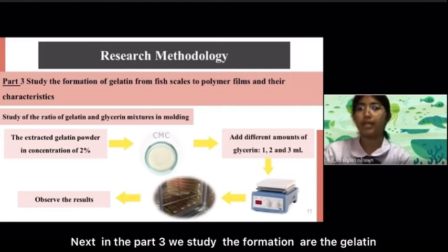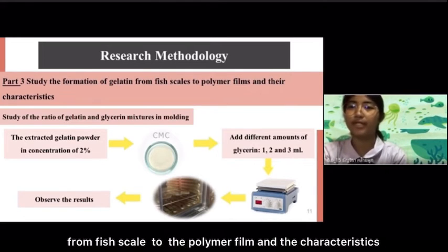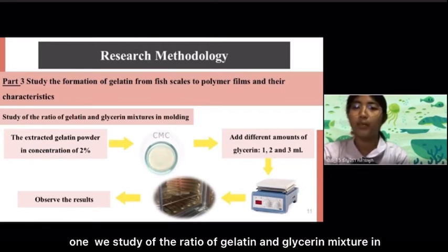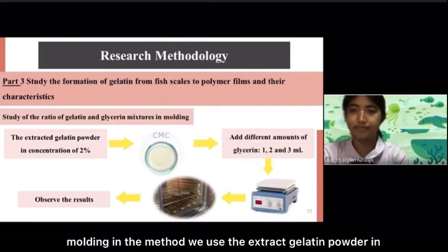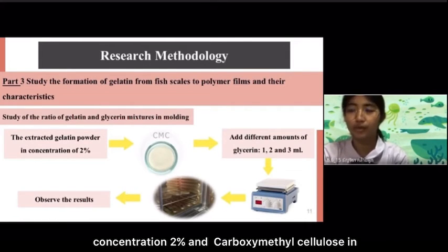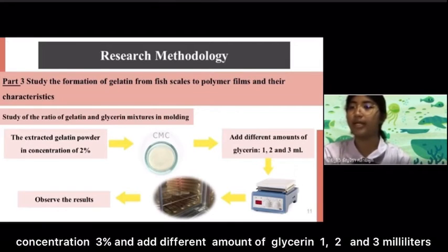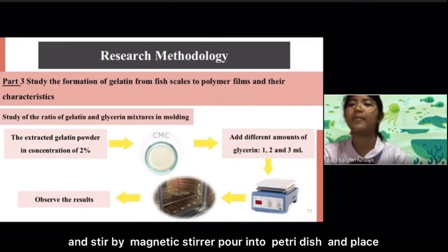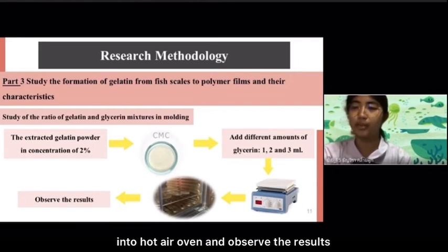Next, in part 3, we study the formation of gelatin from fish scale into polymer film and its characteristics. 1. We study the ratio of gelatin and glycerin mixture in molding. In the method, we use the extracted gelatin powder at 2% concentration and carboxymethylcellulose at 3% concentration and add different amounts of glycerin, 1, 2, and 3 milliliters, and stir with a magnetic stirrer, pour into a petri dish, and place into a hot air oven and observe the result.